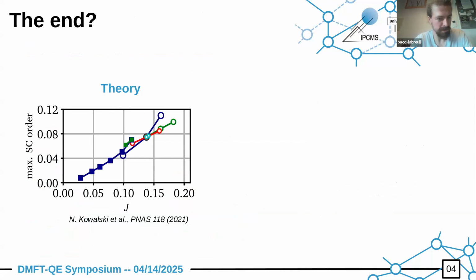I think that a very simple example will be this one. If I take one plot from this work of Kowalski and collaborators, where we see on the y-axis the maximum superconducting order parameter, say that would be basically your density of pairs in the system, versus the super exchange J, the theory tells you quite nicely that you should expect a quite simple correlation. The higher the super exchange, the higher the density of pairs. So you would think the greater the superconducting properties.